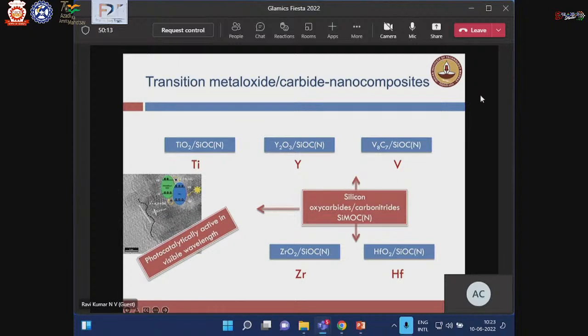We have already investigated quite a bit in situ crystallizing transition metal oxides such as hafnium and zirconium and making them highly thermally stable. Currently we are working on in situ crystallizing yttria, vanadium carbide and so on, again for specific structural applications. We have extensively worked on in situ crystallizing titania in silicon oxycarbide, and as I said, it is very much possible to stabilize such metastable phases over a wide range of temperatures and fine tune them for functional applications. Just to give you an idea, in situ crystallized titania in silicon oxycarbide is really active in the visible wavelength, which otherwise it could not have been.